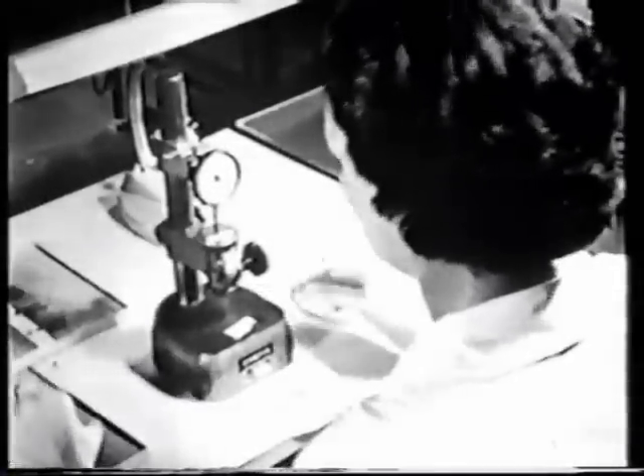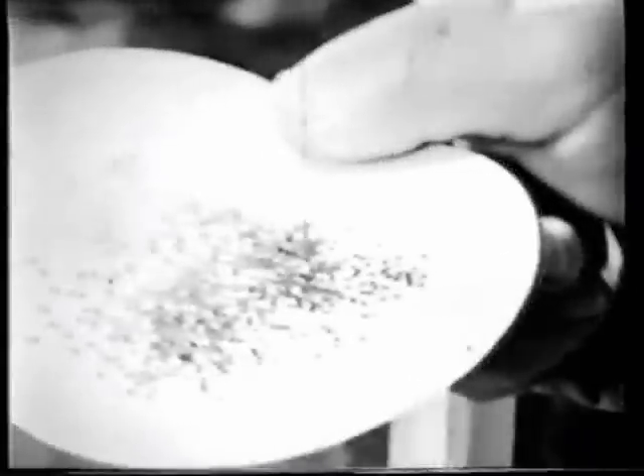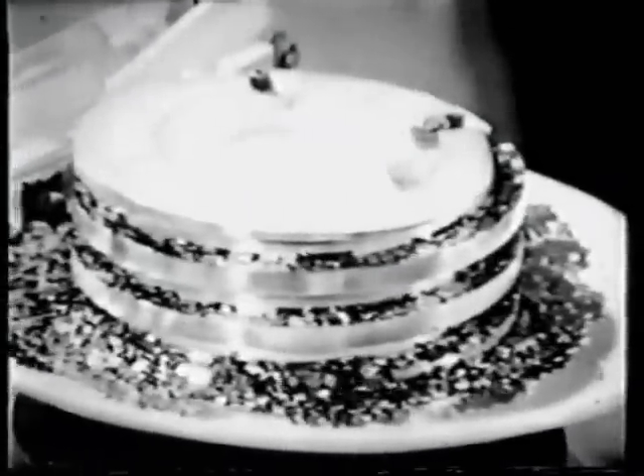The heart of the transistor is a tiny pellet of germanium. Highly refined wafers of this quite rare material are accurately measured, then, after being mounted in wax, are scribed into tiny squares. After separation, the squares are fed into a roller micrometer to be graded in size. This machine is capable of separating squares which differ in thickness by less than 1/10,000th part of an inch. Precision indeed, and vital for satisfactory performance.